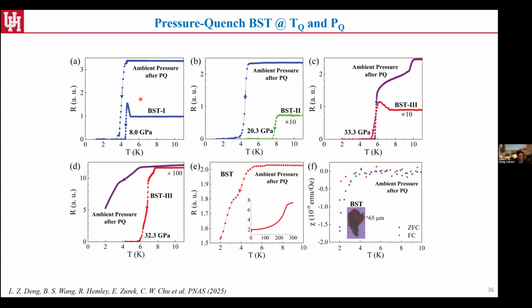So BST has been one of the first samples we're able to recover from the DAC and measure in the SQUID. That also shows superconductivity, even though the signal is very weak, due to the extremely small amount of the sample, a very thin layer, and also that's the largest piece we're able to retain at that moment. So overall, it's a very exciting result. We were able to retain superconductivity from pressure quenching from all these 3 different phases, and it's proved to be a bulk effect, and it can even warm up to room temperature.